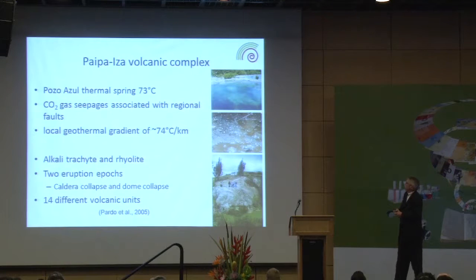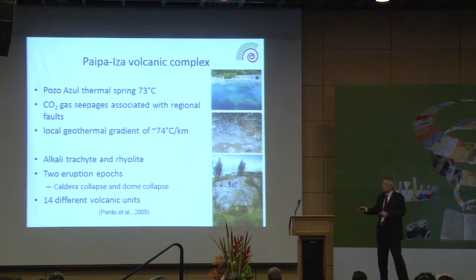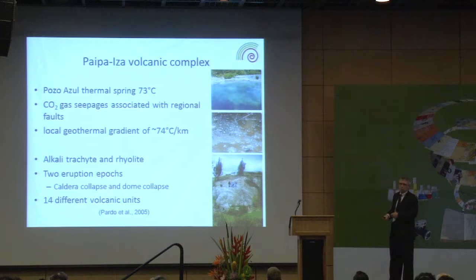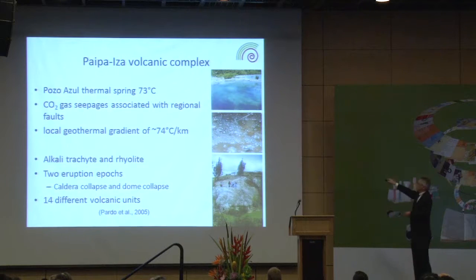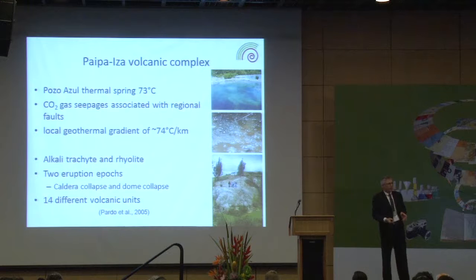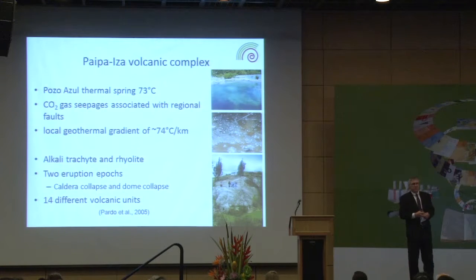So what is the Paipa-Iza today? We have strong thermal activity in this area. We have the Pozo Azul thermal spring, which has a temperature of about 73 degrees Celsius. We have CO2 gas seepages that we can see in certain areas where the CO2 comes out of the ground. We have a local geothermal gradient that was determined at about 74 degrees Celsius per kilometer.